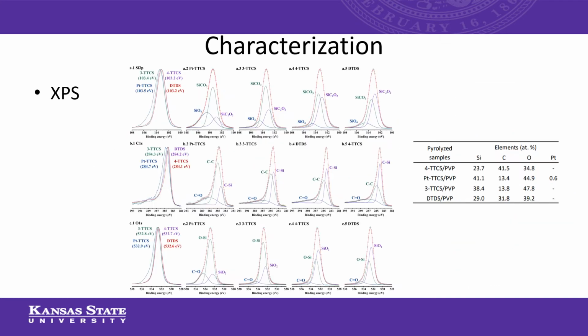XPS is performed firstly to determine the overall composition of the final product. As you may see, the platinum TTCS sample has the highest silicon concentration. And then this may later affect the flame testing. So one thing to notice is that, as we mentioned in Raman spectroscopy, the platinum TTCS sample has a very strong G band than D band. And this can be confirmed here that from the high resolution scans, platinum TTCS samples always shows the lowest carbon to silicon bonding, which indicates the phase segregation of this product.